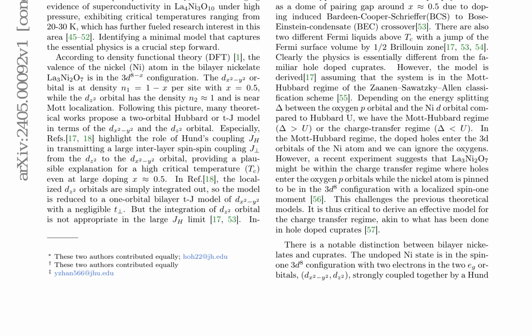In the context of bilayer nickelates, La3Ni2O7, a theoretical study reveals the crucial role of the Zhang-Rice spin-half state as the dominant hole state. The type 2 t-J model emerges as a minimal model for both bilayer and trilayer nickelates, distinct from hole-doped cuprates due to strong interlayer spin-spin coupling. This leads to an optimal doping of 40 to 50% in the bilayer type 2 t-J model, contrasting with 20% in cuprates.